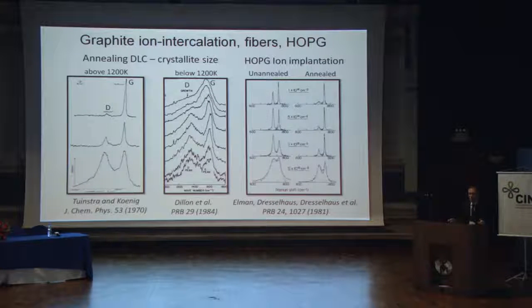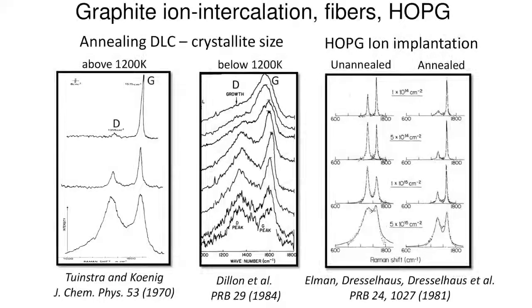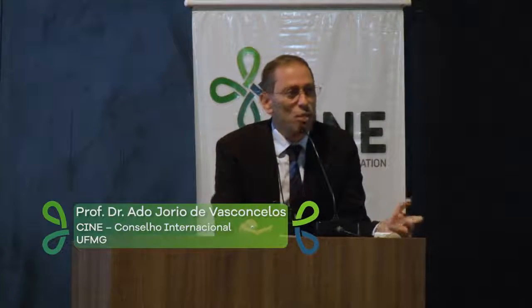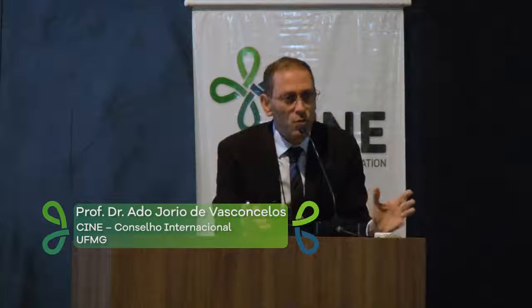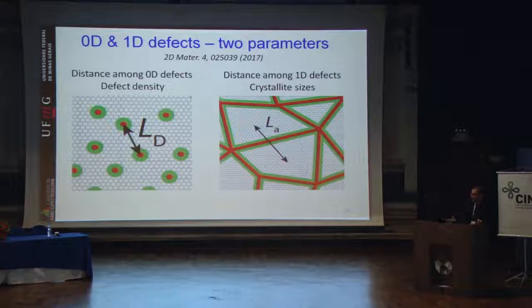Also, on the quality of graphite that you can see from Raman spectroscopy, this signature of, we say, the intensity of the disorder peak with respect to the graphene peak, this is largely used by many. I saw many presentations here where they would look for this aspect. And what we are doing in collaboration with Inmetro and some other institutions is trying to make this thing very well stable, very well understood. And basically, when you think about defects on a two-dimensional system, these defects can be like points, like a vacancy or a functionalization, or they can be grain boundaries in nanocrystallites.